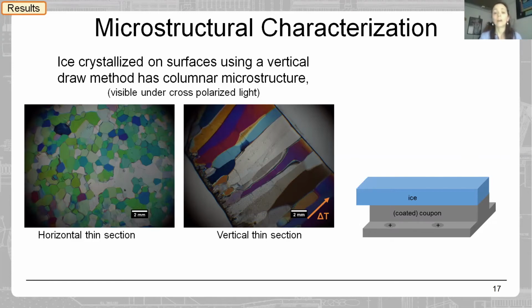Right now what we're working on is determining what the crystallographic orientation is of these grains. Tony Gao, who Zoe introduced you to, was able to show that this is exactly the same kind of microstructure that grows on the surface of still rivers and lakes. Depending on the conditions at the time of growth, you can have the C-axis of the ice lattice oriented along the length of the column, but you can also have other growth conditions where the C-axis is oriented horizontal to the growth, the long column of the grains. We're working on characterizing that so we can better understand the structures.